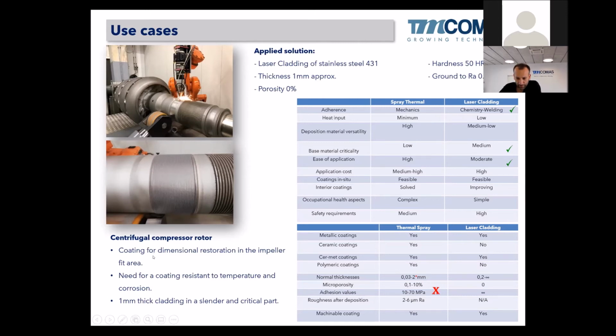So yeah, we need a coating with a material resistant to temperature and corrosion, because this compressor rotor works in an ammonium plant, so it was compressing some ammonium gas or something like that. So it was some corrosive gas here, and also at high temperature. So the applied solution was to apply a laser cladding of stainless steel 431, which is a martensitic with 50 HRC